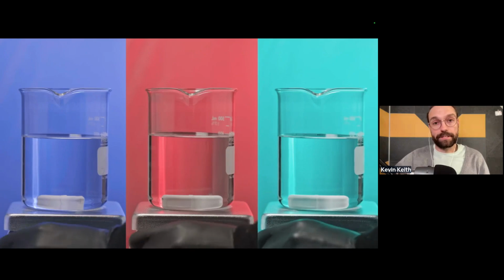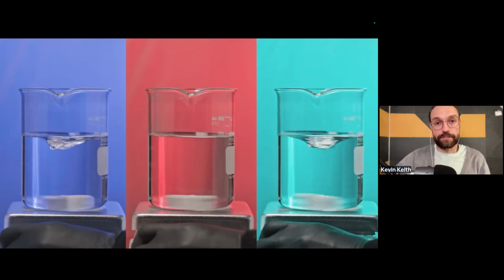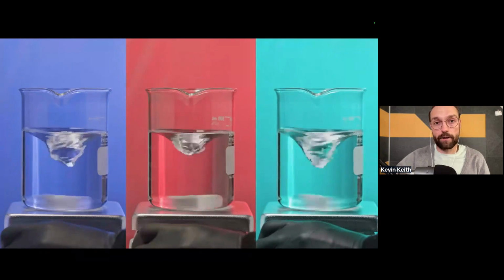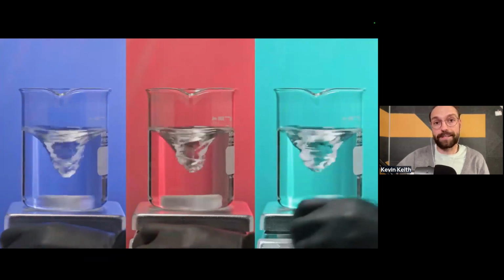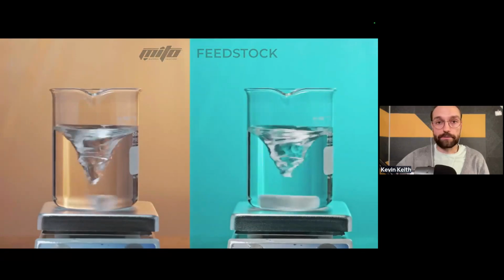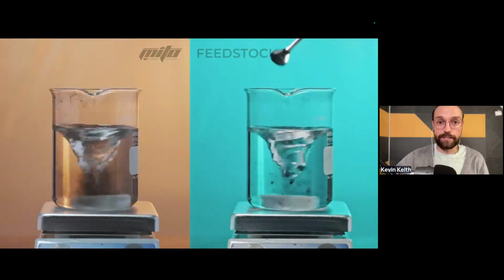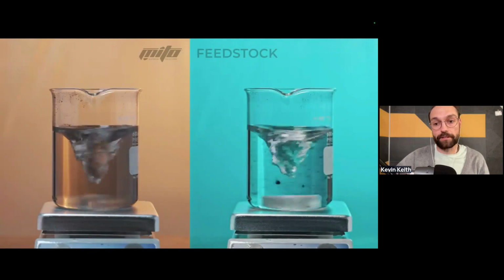Now, what that really means with other graphene feedstocks is here you'll see 3 different colors, and they're all different graphene feedstocks ranging from nano graphite all the way down to few layer graphene. On the left in the yellow is that same feedstock functionalized with our chemistries.